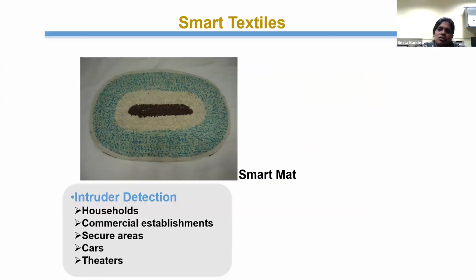In the case of woven samples, we have got various ranges of conductivity, from 20 to 7,000 ohms per square. As I told you, we can use it for smart textile applications and heat generation. So based on the achieved resistivity, we have developed some prototypes. One is this smart mat. Here we have placed our polypyrrole coated sample inside this mat, and we checked its performance as a switch or as a pressure sensor. This is basically called a smart mat.